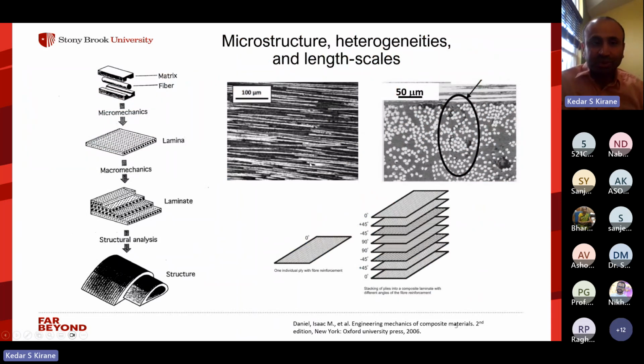Essentially, they consist of two materials combined, the matrix and the fibers. And so these are some micrographs showing the heterogeneities in the microstructure. You can see, maybe on the right, that within one layer of the composite, there are many of these fibers, and micrometer order is the size of these fibers, a few microns. Now, composites generally are made into lamina, like layers, and then they are stacked with different orientations. So each layer, if you think of it, most common is a unidirectional lamina where all the fibers are running in one direction. And that makes it very, very anisotropic.